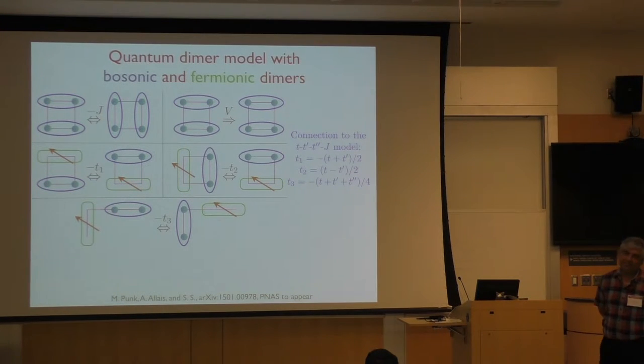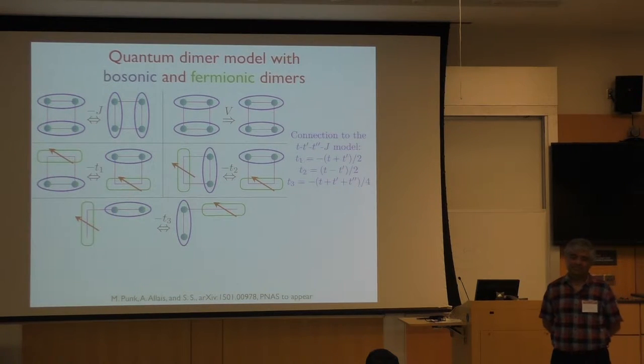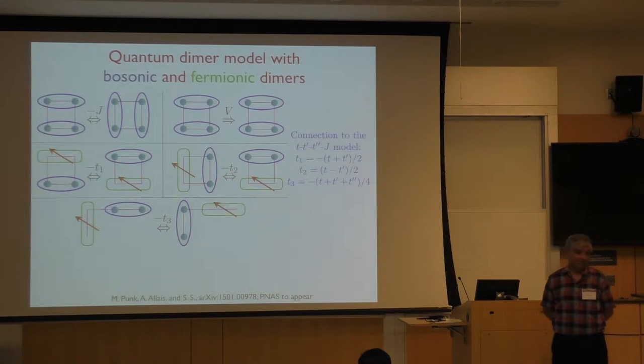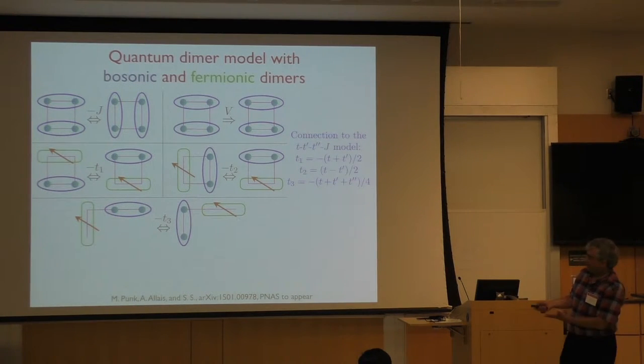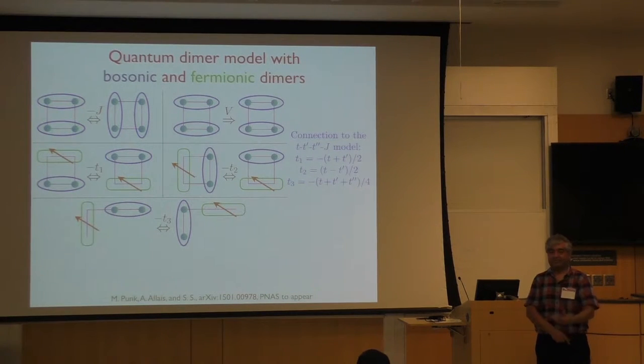Question: Can you imagine the topological order is in a way not stable to finite temperature? Answer: Yes. The pseudogap is associated with high temperatures. So all these statements of Fermi liquid theorem and so on are only zero-temperature statements. But for all the world, it looks like the pseudogap regime is behaving like an almost zero-temperature state — certainly in the T-squared dependence of all the transport properties: omega-squared and H-squared, all very conventional.